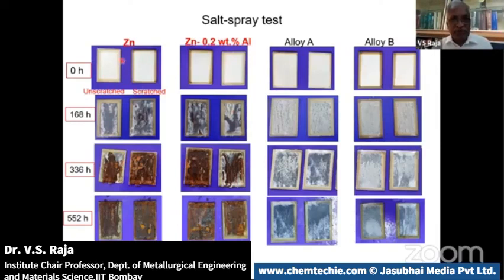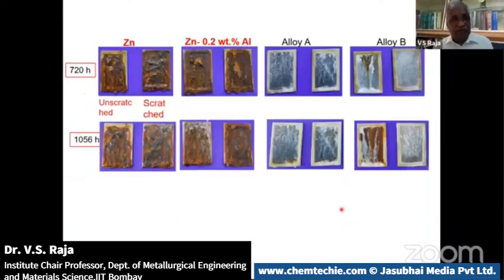I'm giving you only a simple diagram for you to appreciate it. This is for pure zinc. This is the normal zinc hot dip galvanizing coating, alloy A, alloy B coatings, with only 0.028% element added. Look at this, 168 hours, rusting here. Now 552 hours, no rusting taking place. Look at the kind of increase. Not only 552, it has reached almost 1056 hours, and you don't see much increase in the corrosion of these coatings. So you can simply tweak it by adding a small element.